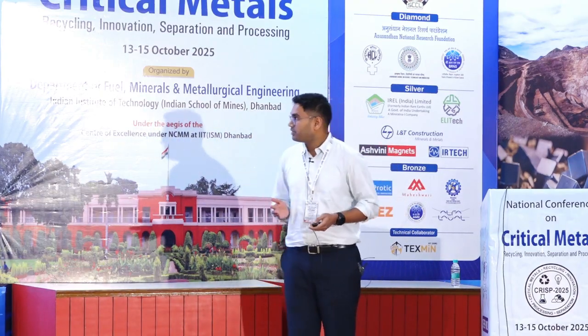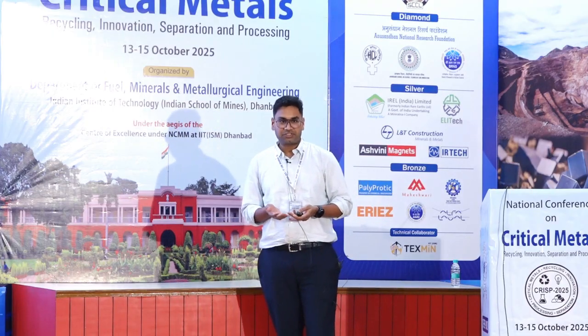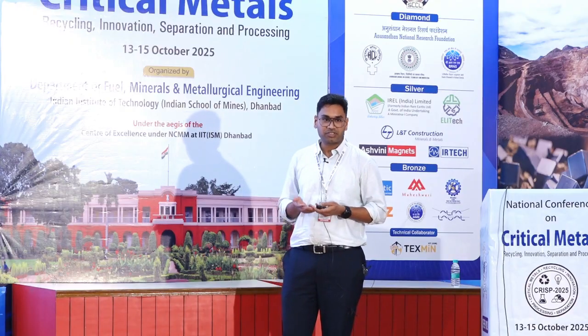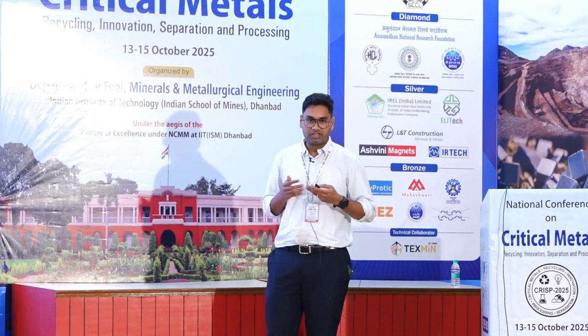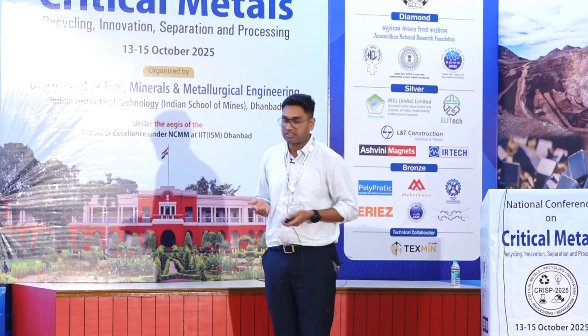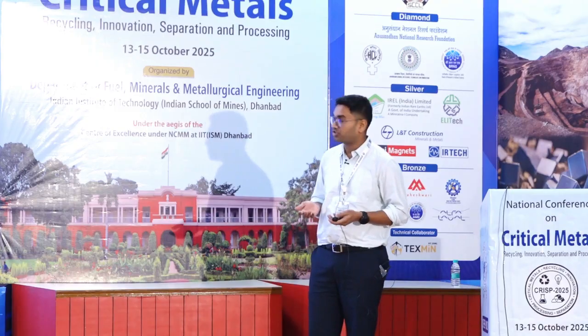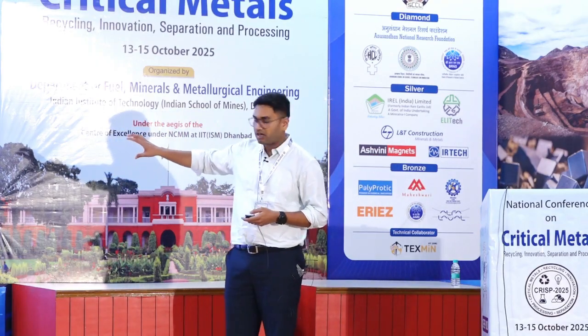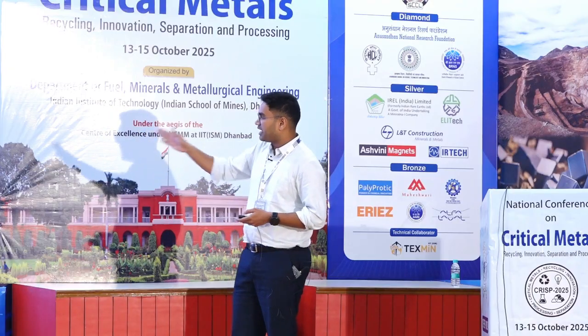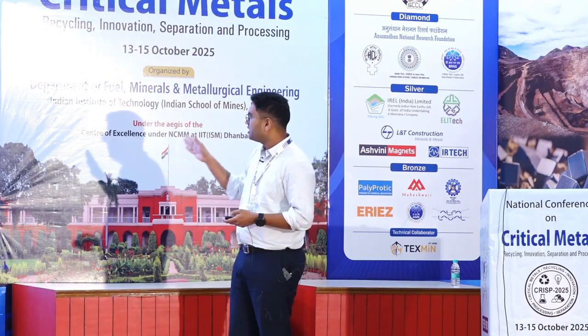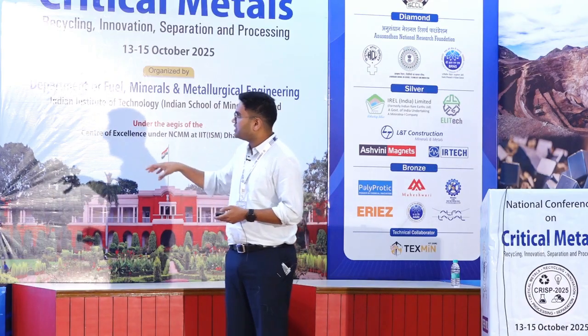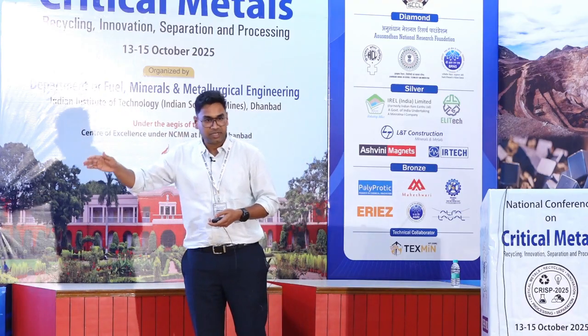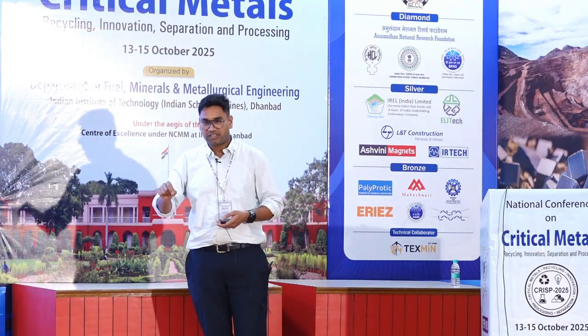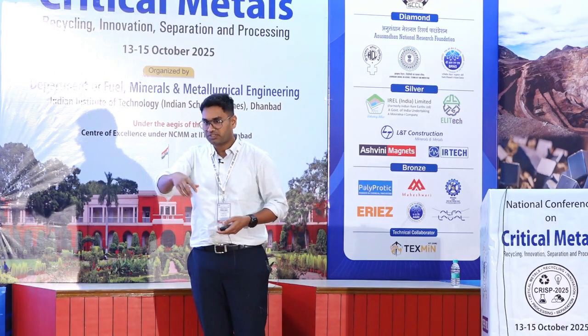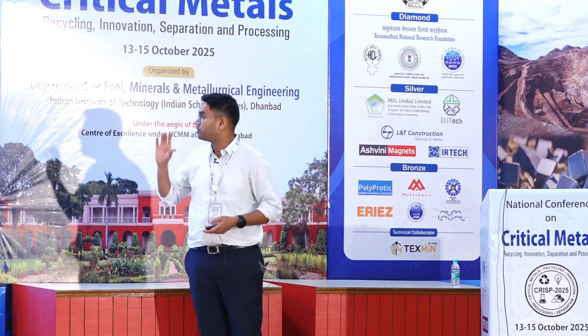So the flotation in itself is a very complex process. I did my PhD in flotation, so I can say that it consists of more than 30 variables which are changing at a single unit of time, and therefore it leads to some challenges in the recoveries or the efficiencies of this process, which is majorly represented by an elephant curve. In this case, if the particle size is more than 100 or 150 microns, then because of the turbulence in the mechanical cell, the recoveries of these particles drop. When the particle size is less than 10 microns or 20 microns, then these particles are like inertialess, and that's why they are just moving along with the feed or with the fluid itself, and therefore they never see any bubbles to attach with, and therefore the recoveries are low.